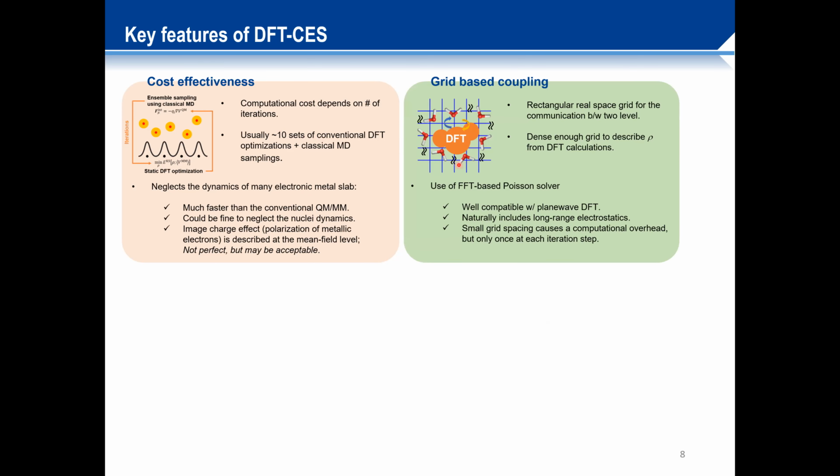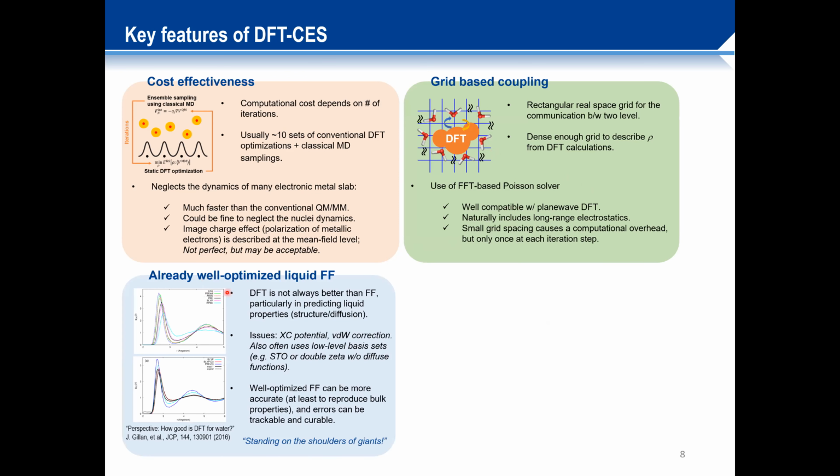Also, we are using a grid-based coupling, which includes an FFT-based Poisson solver. So it naturally includes the long-range electrostatics. It also has good compatibility with plane wave DFT, which is good for modeling solid systems. Also, we rely on a well-optimized liquid force field.